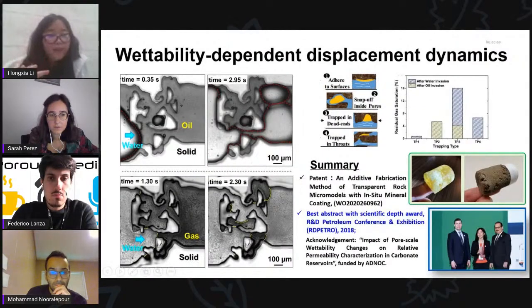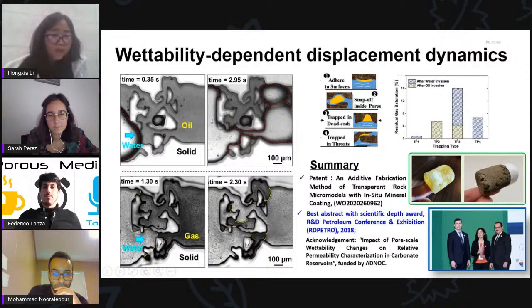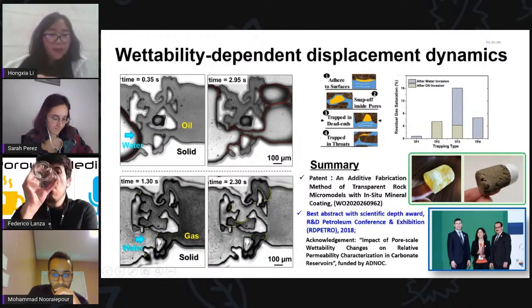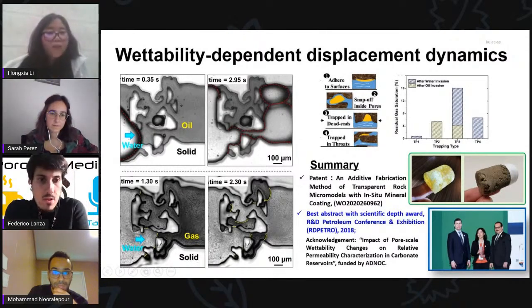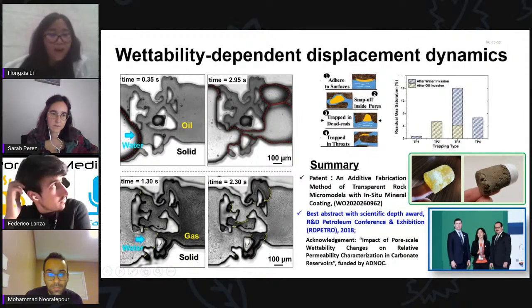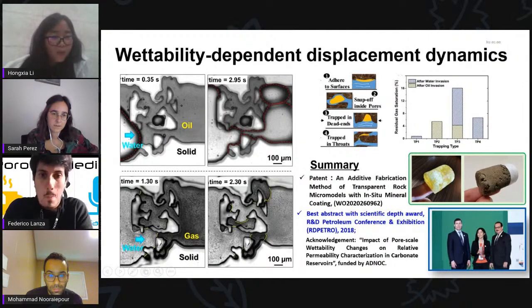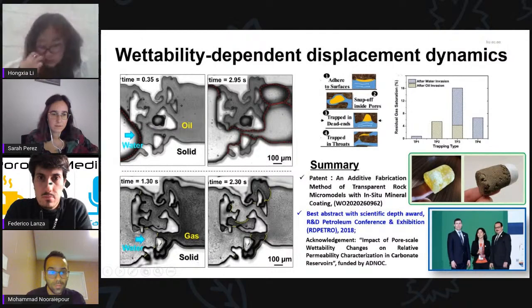With all this work, once we get this mineral-coated microfluidic chip with the pore-throat networks we printed, we can continue to study multiphase flow. Here is one example, mimicking the oil recovery process. We inject water into these channels, and see how the oil is trapped there, and how much or how fast the oil is replaced out. We can also do water replacing gas entering the empty channel. Because the mineral coating is intrinsically water wet, we can see the meniscus curvature results in some capillary pressure, which helps the water enter the channels.